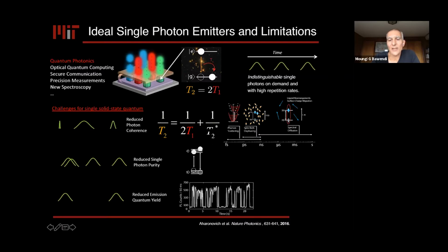This could be if the electron sitting in my box interacts with vibrations that are inside the box. They scatter off vibrations, or the electron has a spin, and if there are atoms in there that also have spin, that is the equivalent of a spin bath, and there could be an interaction between the spin of the electron and the spins inside your lattice.